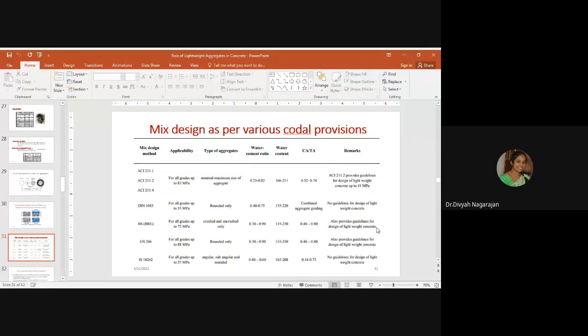DIN code of practice is applicable for all concrete grades up to 55 MPa, and it restricts the type of aggregate to rounded only. The water cement ratio is between 0.4 to 0.75. Water content of 135 to 220 kilogram per meter cube is allowed, and combined aggregate grading is adopted in this method. No guidelines for design of lightweight concrete are provided.